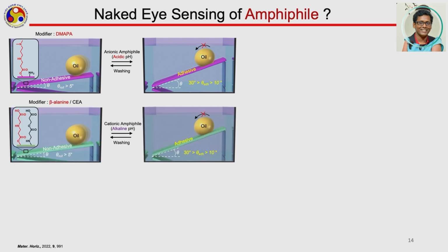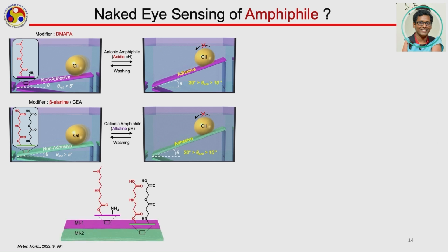She also did another control study where she introduced these two carboxylic acid groups. At alkaline conditions, they can dissociate and give the negative charge. Now you introduce a cationic surfactant. What will happen? The cationic head will interact with the dissociated charge of this carboxylic group, and it will also provide the hydrocarbon tail to interact with the beaded oil droplet, and that's the way you will see this change in the adhesions. So next, she developed a patterned interface where half of the coating was introduced with modification 1, which has these cationic functional groups, while the other half is modification 2, where you have these carboxylic acid groups, and in alkaline condition they can dissociate, right, and give the negative charge.